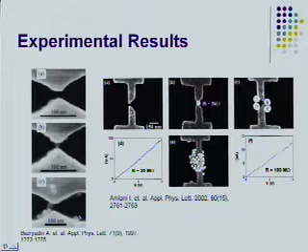Hit the next one. And these are some results. On the left you see an earlier study that used palladium particles, and they were able to get trapping of sometimes single particles, sometimes a couple of particles bridging. This actually didn't use molecules yet. On the right they had studies with a molecule-coated electrode, and then they trapped gold particles. An interesting thing is that as you increase the particle radius to the size of your actual gap, most of the time only one particle traps in there, because once you trap, you condense the field to that particular point where they bridge.